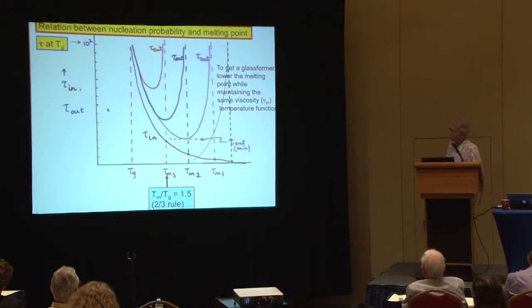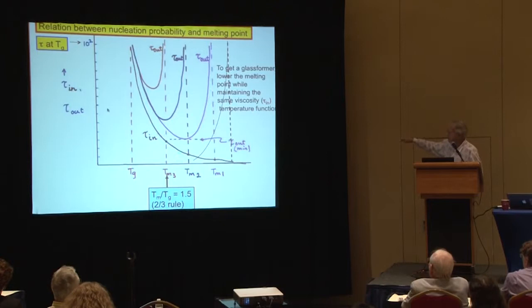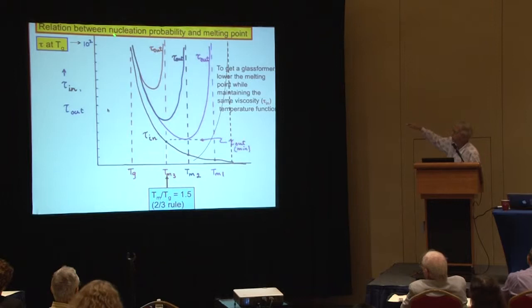What you do is reduce the melting point, change the liquid if you like, or in the case of our systems, we add a second component, without changing the internal relaxation time. If you do that, then you change the temperature at which you start to get a finite escape time, and as you make the melting point lower and lower, close to the glass transition, the TTT curve gets squashed out, and the minimum time for crystallization gets pushed to longer and longer values. The aim of the glass former is to push it beyond this 10 to the second power characteristic of the glass transition. Then you've got a really good glass former.